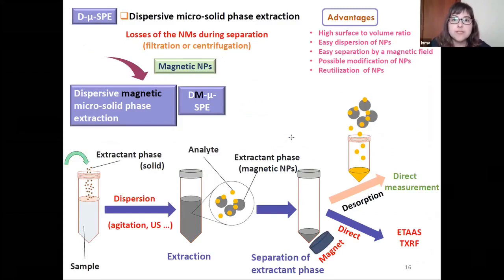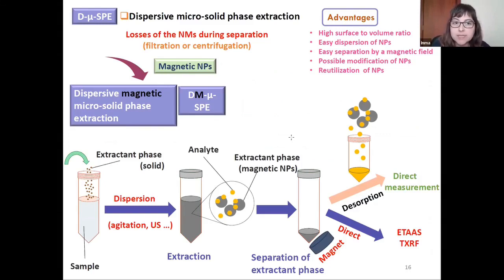However, dispersive micro solid phase extraction has some problems, such as the loss of the nanomaterials during these separation steps, mainly filtration or centrifugation. Thus, an alternative could be the use of magnetic micro solid phase extraction, with magnetic nanoparticles, that has different advantages, such as the easy dispersion of the nanoparticles and easy separation of the nanoparticles from the aqueous solution by using a magnetic external field. Also, it is possible to modify these nanoparticles by functionalization, for example, and sometimes it is possible to reuse these nanoparticles.